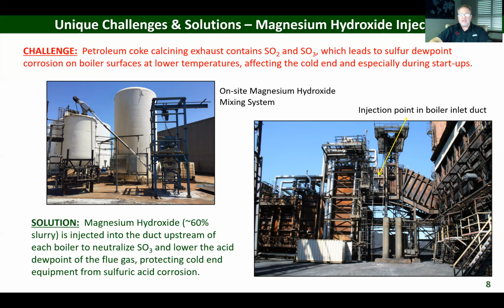In general, we try to keep our stack temperature at 400 degrees or maybe even slightly higher to make darn sure we stay well above the sulfur dew point, and not only in the back end of the boiler, but also through the multi-clone, the induced draft fan, the stack, all of that, which is all carbon steel material. We've got to avoid the sulfur dew point. The other thing, and this is what's pictured here, that we do that's unique is we inject a roughly 60% slurry of magnesium hydroxide upstream of each boiler. You see there the location where we inject it in the ductwork just ahead of the radiant section of the boiler. We do this at each of the three boilers.